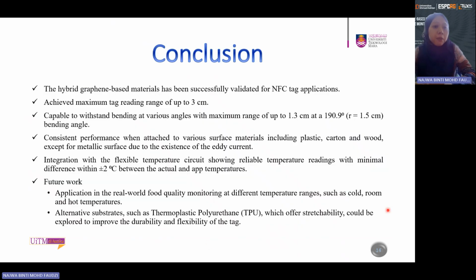In conclusion, the hybrid graphene-based material has been successfully validated for NFC tag application, and the maximum reading range achieved is 3 centimeter. It is also capable of withstanding bending at various angles, with a reading range of up to 1.3 centimeter at 190 degrees of bending. Consistent performance has also been observed when the tag is attached to various materials, including plastic, carton, and wood, except for metallic surfaces due to the existence of eddy currents. The integration of the flexible circuit also shows temperature readings with minimal difference, within plus minus 2 degrees between the actual and the app temperature.